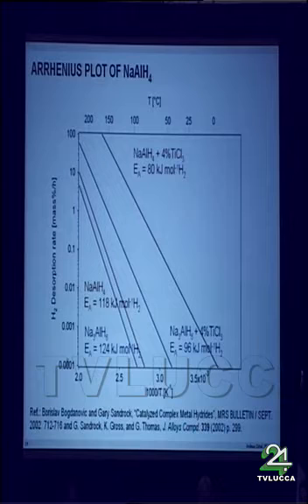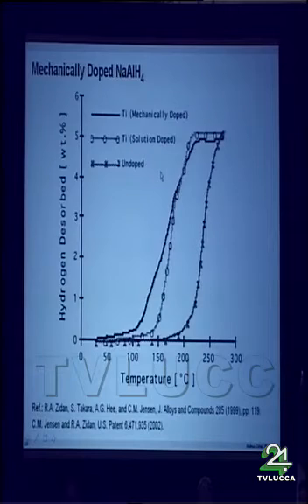Now, when you calculate the activation energy again for the non-catalyzed and for the catalyzed sodium aluminum hydride, you notice that the catalyzed sodium aluminum hydride has an activation energy for the hydrogen desorption of about 80 kilojoules per mole. So again, it's in the same range as I showed before for aluminum hydride, and many others have values in this range. And there was, you can see here, a significant reduction of the activation energy due to the catalyst.